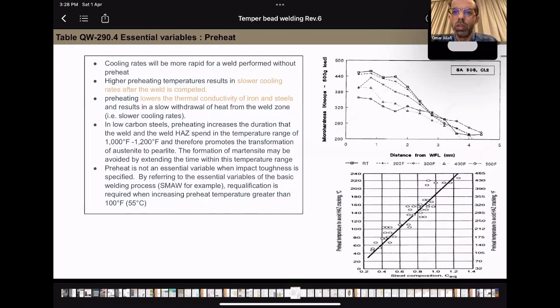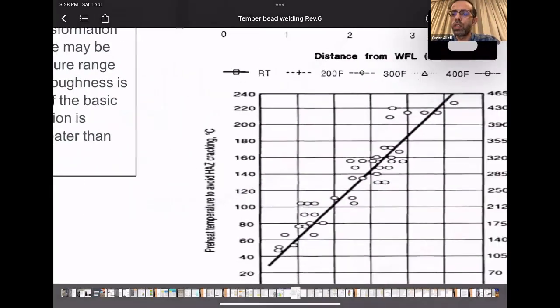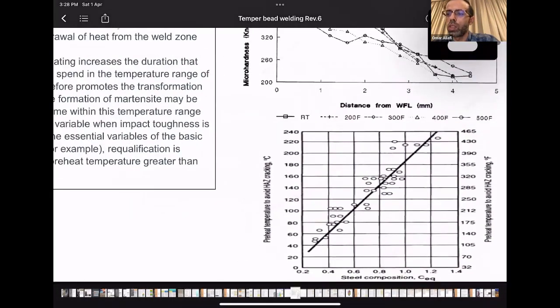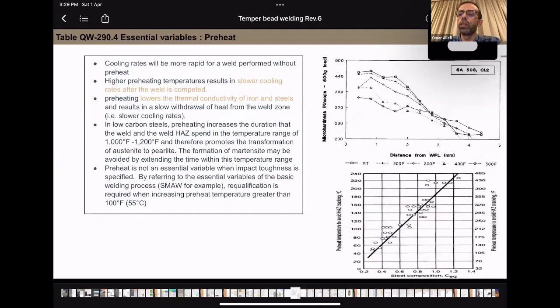Okay. So this chart, in this chart, you can see how steel composition and carbon equivalent determine the preheat temperature required for any carbon equivalent. This is, of course, again, because it is required when hardness is specified. So the preheat temperature can be estimated using this chart. This is how we can estimate the preheat temperature for a steel material.